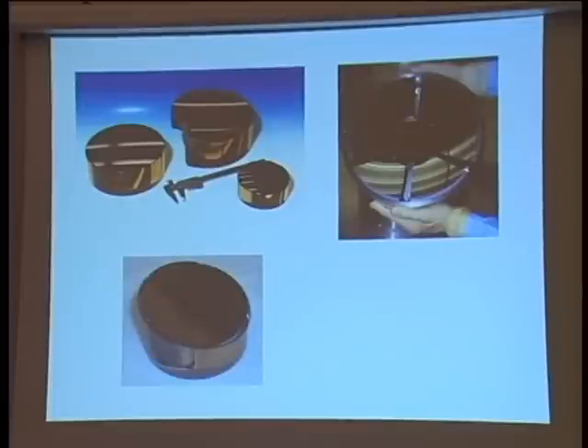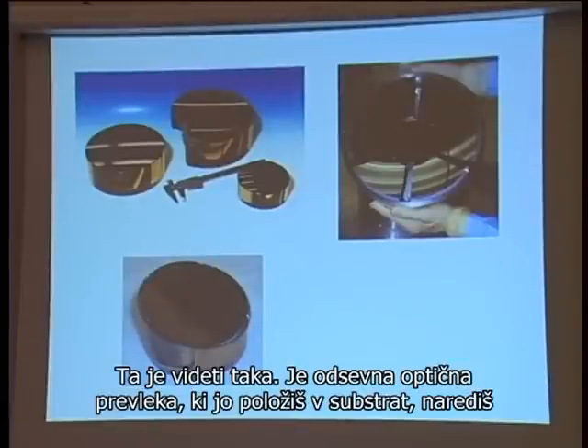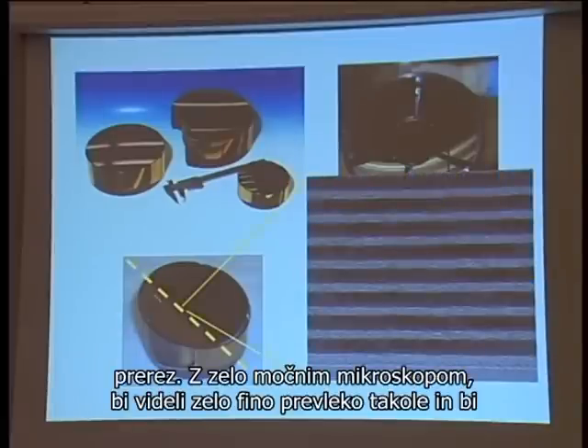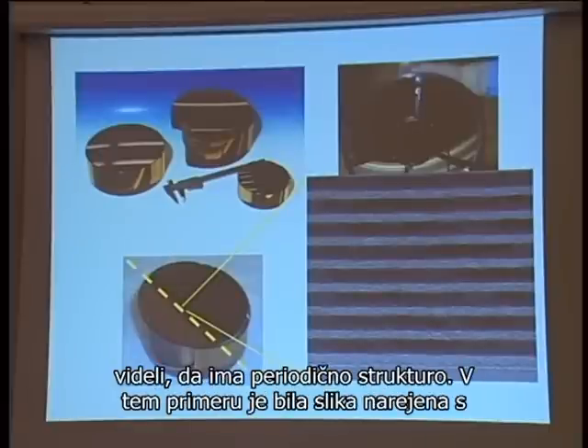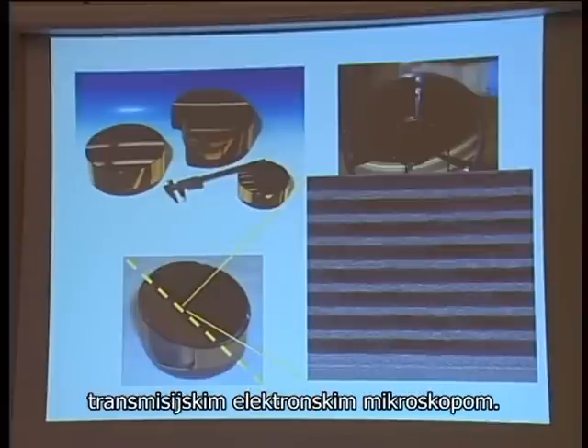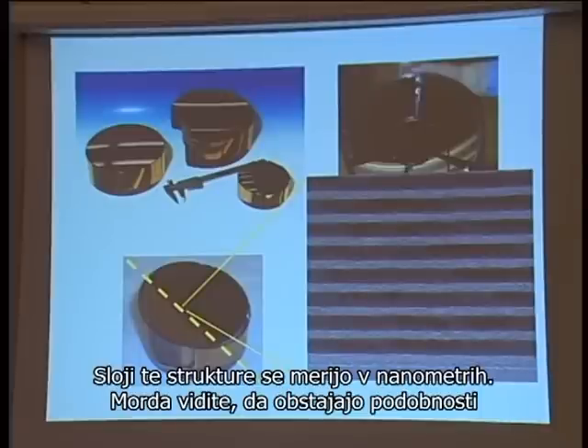So multi-layer optic, usually, it looks like that. It's reflective optic, a coating that you put on a substrate. So if you cut it in cross-section and look just at the thin coating that you have here, under a very powerful microscope, in this case a transmission electron microscope, you would see that it consists of a periodic structure with very thin layers, where these layers are on the order of a nanometer or so.